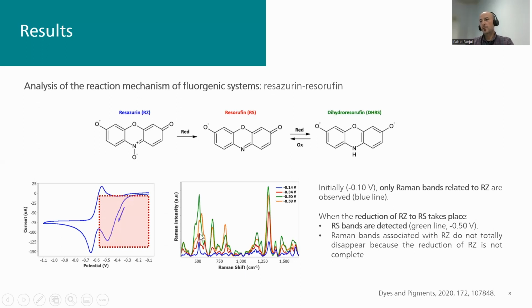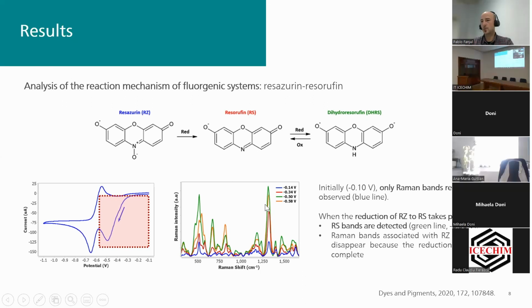In this case, if we start with the Raman spectrum in blue, which is the one that we have at these initial potentials, we can see that during this reduction, during this electrochemical process, it is moving from the blue to the orange one. So at a specific Raman shift, for instance here, we can see the evolution of the Raman band, and we can see it here as well.